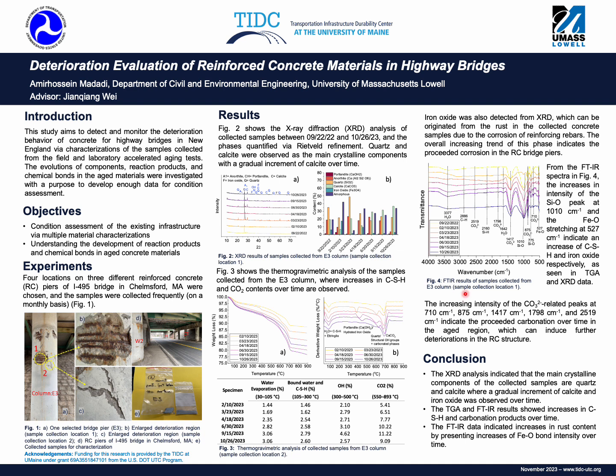The next analysis that we have done in this study is Fourier transform infrared spectroscopy, which is used to identify molecular compounds, and it works by measuring the absorbance and transmittance of infrared radiation by a sample. The resulting spectrum can then be used to identify the functional groups and chemical bonds which are present in the material. In figure 4, our FTIR spectra indicate increases in the intensity of the Si-O bond at, for example, 1010 cm⁻¹, and also the Fe-O stretching at 527 cm⁻¹. These findings align with the elevated CSH content and iron oxide content observed in the TGA and XRD data.